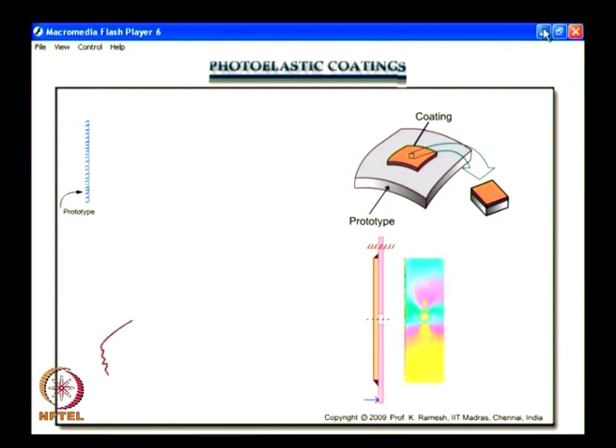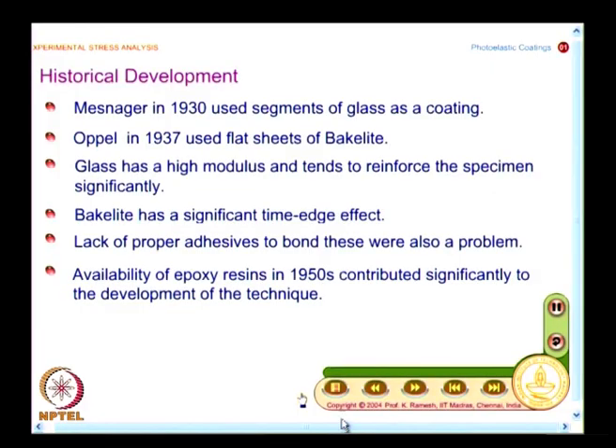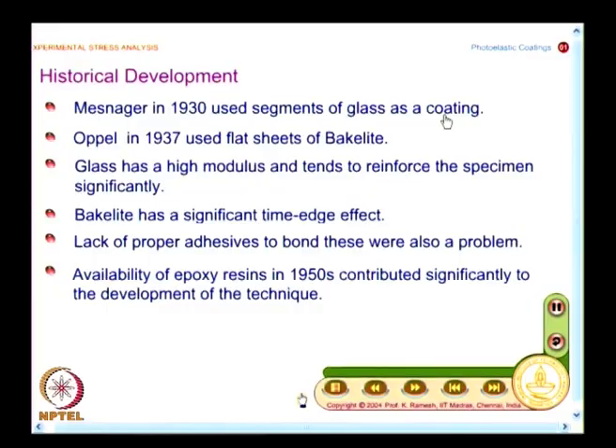And if you look at any of the techniques, we need to look at the history behind it. And what you have as historical development, we have Mesnager in 1930 using segments of glass as a coating. It is very surprising, you know, we have looked at photoelastic materials and glass is also a photoelastic material, and it has a Young's modulus of 70 GPa, equivalent to aluminum, whereas all other plastics we had only 3 GPa. And because this has a very high value of Young's modulus, one of the problems with glass was that it reinforces the specimen significantly.